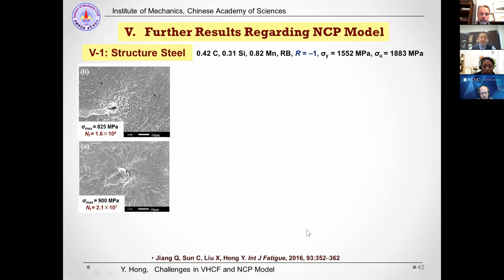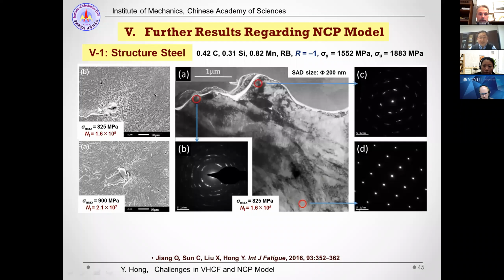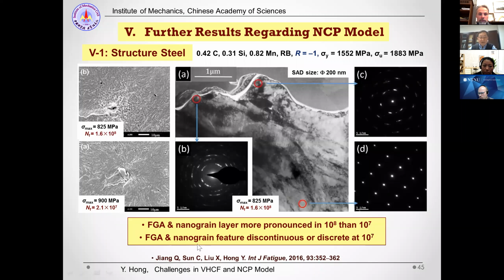The first one is structural steel, because the previous cases were all steels with high carbon contents, and this one has a medium carbon content. We see that at 10 to the 8 cycles of loading, the rough surface of the initiation region is quite well developed, but at 10 to the 7 cycles it is less developed. We also observe that this region has a refined microstructure of nanograins. So the FGA and nanograin layer are more pronounced at 10 to the 8 cycles of loading, but less pronounced, discontinuous, or discrete at 10 to the 7 cycles.